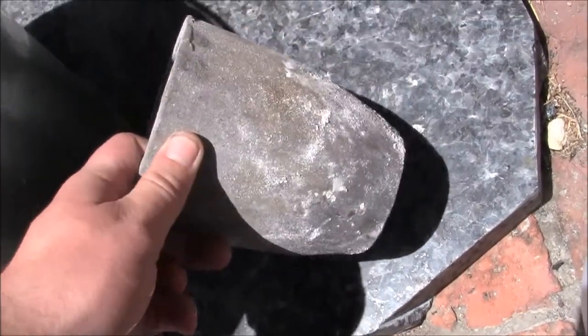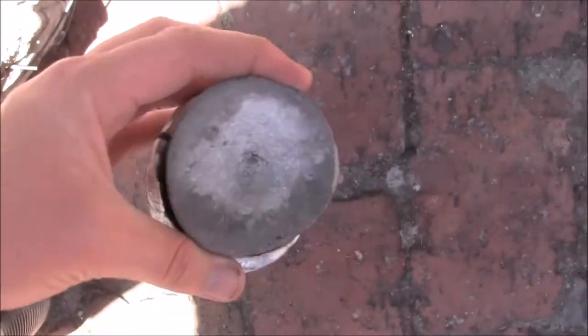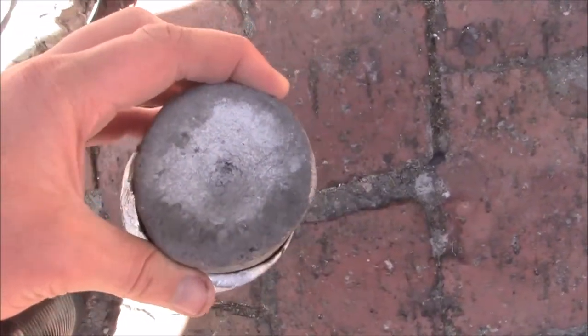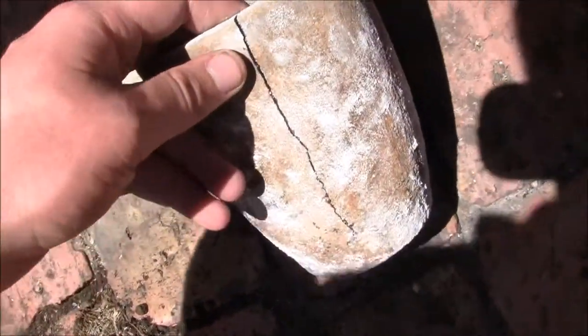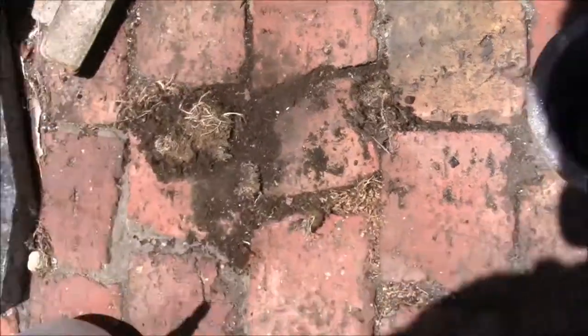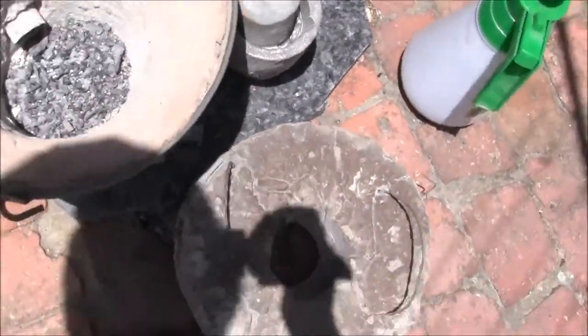I'm going to be using this as my crucible — it's a clay graphite crucible. It's the second one I've had to go through so far, because when I was trying to melt some aluminium, I had a piece that was a bit oblong shaped. I put it into the metal I was melting and it acted like a heat sink, sucking out all the heat, and then it thermally shocked my crucible and caused it to crack.